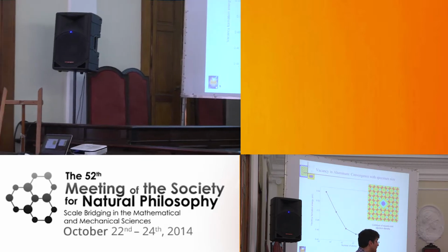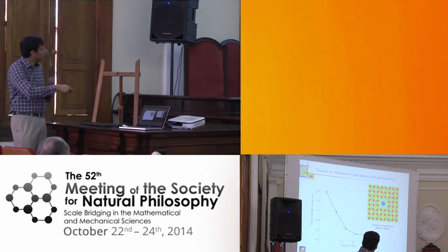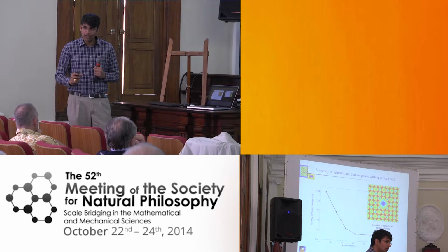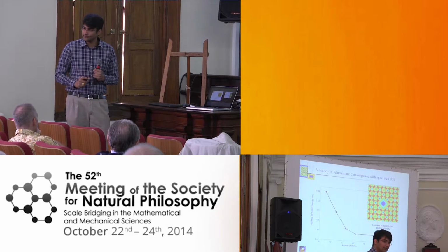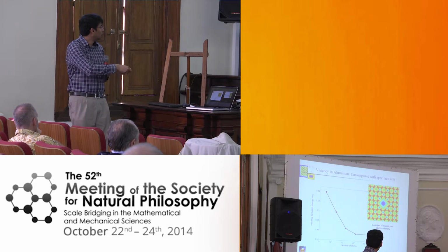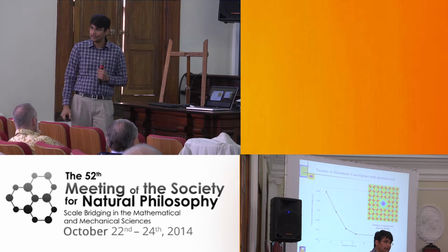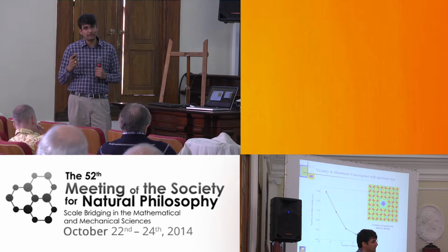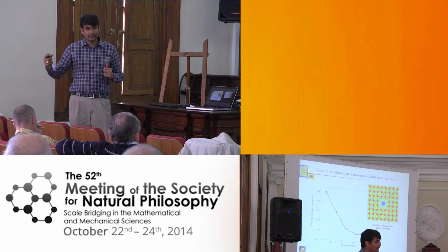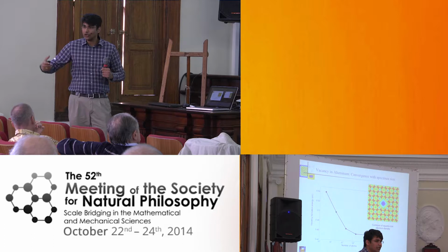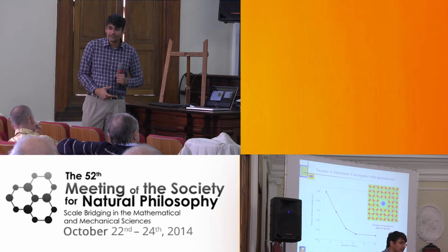This is the total number of atoms in the unit cell. So as you can see, we have to go to about 10^4 atoms, about 10,000 atoms, even to converge for a simple defect like a vacancy. Most of the calculations done in DFT operate in this regime over here at about 100 atoms. And then they use periodic boundary conditions, which means that they're not looking at an isolated defect in the bulk, but they're looking at a periodic array of defects.